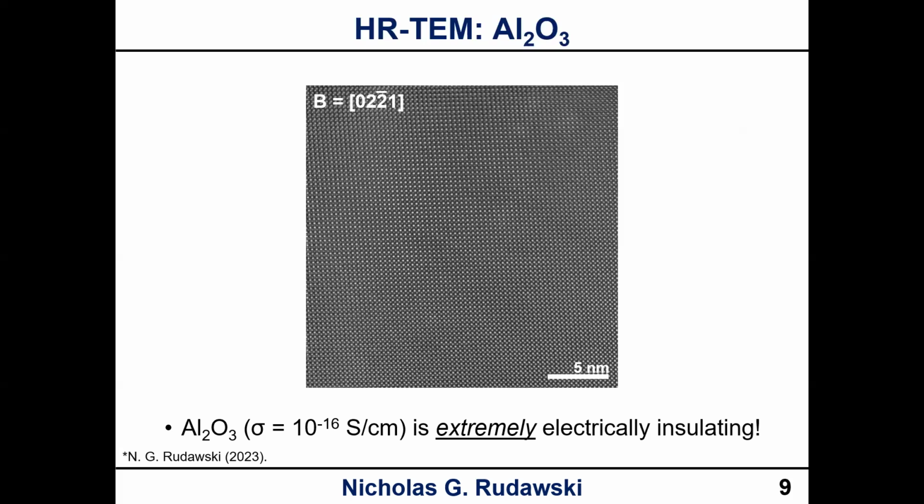So here's your first proof that no charging occurred and there was no conductive coating put on this sample. You never want to do that in STEM. You wouldn't want to put a coating on it because you would be obscuring the detail. It's the same idea behind how we don't want damage layers on the surfaces, or we want to be careful with support films behind particles because those cause a distortion. It would be the same thing if we applied a conductive coating. That would degrade the image quality. The good news is that we don't have to do it because the electrons don't accumulate. They just transmit right through, okay?